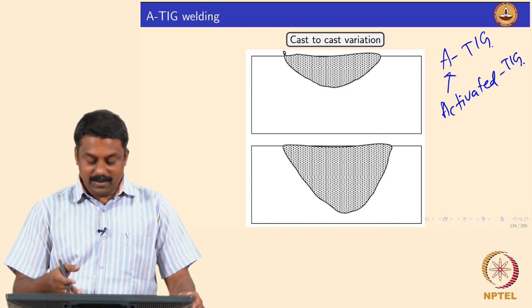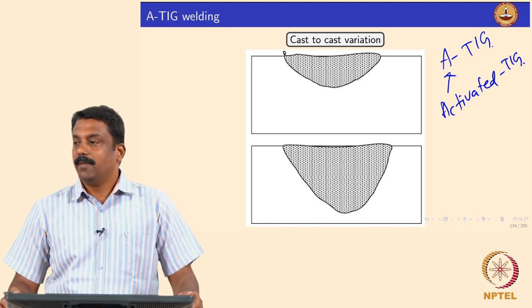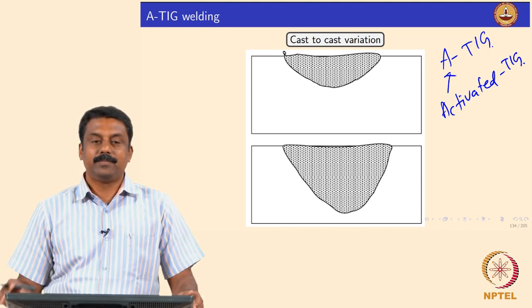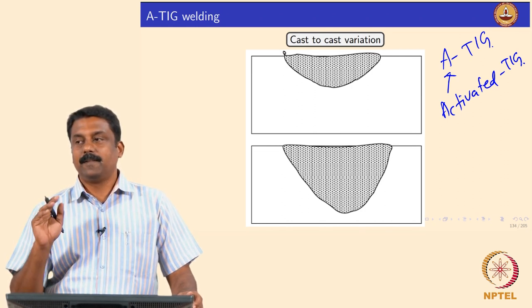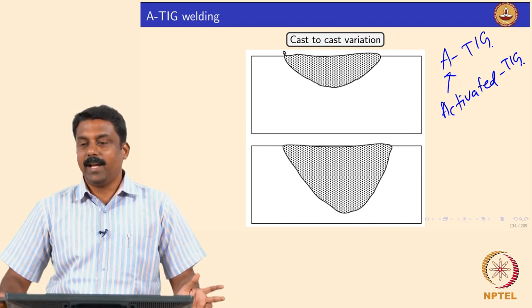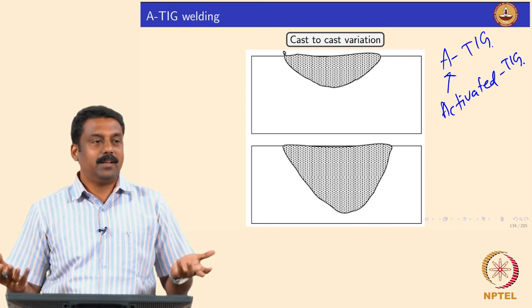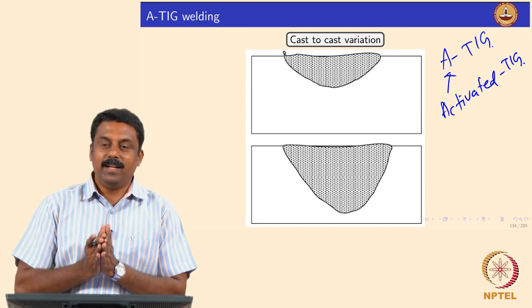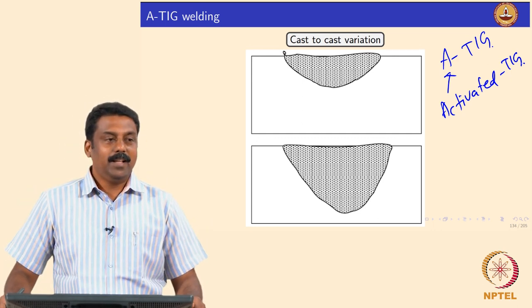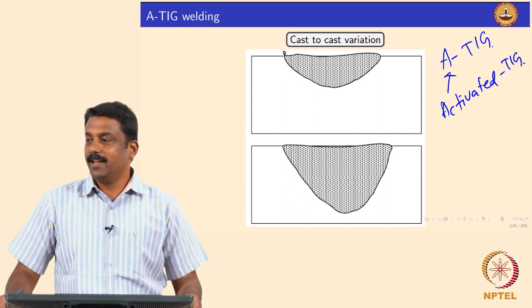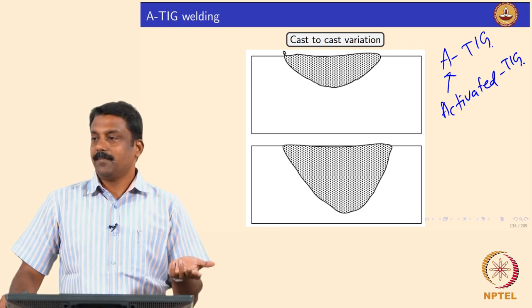For example, I put two diagrams assuming the same composition with a slight change in sulphur — sulphur changed from 0.05 to 0.01. You do not care about it because you always say it is one grade, choosing grade 65 or grade 25 because compositions in the standards are defined over ranges. But in a welding condition, this can cause a significant difference in weld geometry.